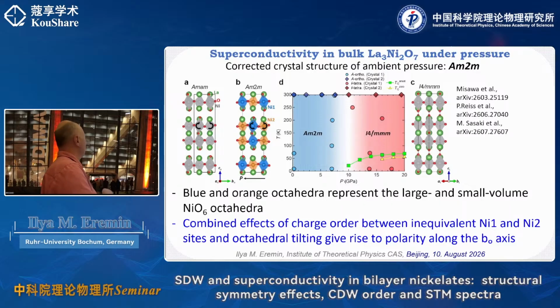So it's orthorhombic, but important is that there are two positions, nickel 1 and nickel 2, in the unit cell in the plane. And they were considered to be equivalent. In this case, crystallographically different, but electronically equivalent. And that has been put into question.